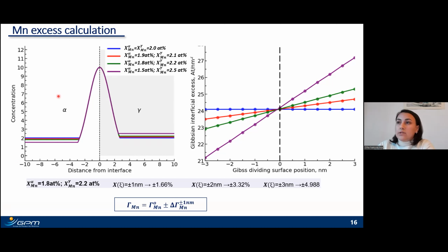And for that, we plotted several test profiles with different compositions on both sides, as you can see here. This difference was chosen with respect to the experimentally observed one. I would like to highlight that in 90% of our cases, we had this situation, meaning less than half of the atomic difference, and the estimation shows, as you can see from this graph, that it is not significantly different. Therefore, in our experimental data, we calculate manganese excess by placing the dividing surface at the peak, but we provide the manganese excess with a deviation corresponding to ±1 nanometer of dividing surface displacement.